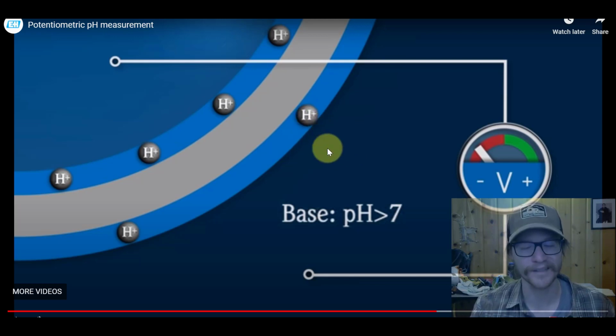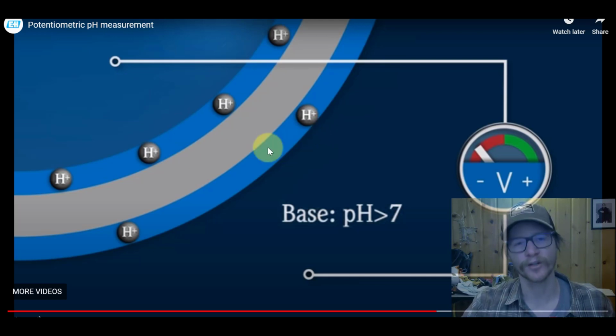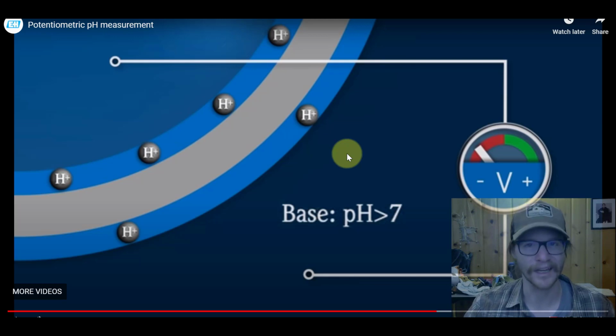So if you've got an ion that's comparable in size, it's just going to diffuse in, and it's going to create the same junction potential between the protons on the inside and, in this case, it's masquerading as a proton. So things like lithium and sodium, if you've got a really concentrated sodium chloride solution and you want to measure the pH of it, you're probably going to have considerable error in that measurement. You won't know, you're just going to read the pH, but know that you run the risk, especially if you've got a lithium chloride solution, which is common in battery science, and you try to measure the pH of those systems. They're almost always in significant error, simply because the ISE is selective, but it's selective from things that are pretty distinctly different in its chemical properties.